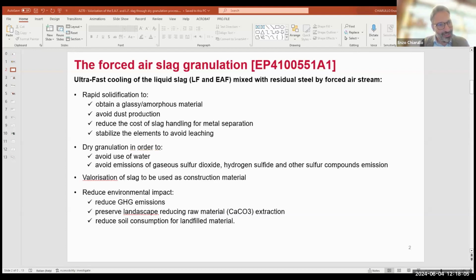Tenova developed this forced air slag granulation, and we obtained a patent since 2017 for a methodology for the ultra-fast cooling of the liquid slag through forced air, in order to obtain a rapid solidification and a glassy amorphous material that can be reused in the construction industry, avoiding dust production and reducing the cost of slag handling because we avoid the disgregation of the slag. Through this methodology, we stabilize the elements, avoiding the leaching, and we also avoid the use of water because we are cooling the slag only with forced air.